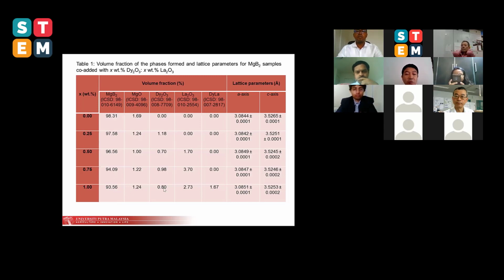And that is also due to the fact that you have the increase of other impurities or unreacted products. As we expected, in this column, the lattice parameters of the a and c axes did not change much. Because of that, we also expect that the Tc would not change much. I will show you the result of Tc later.